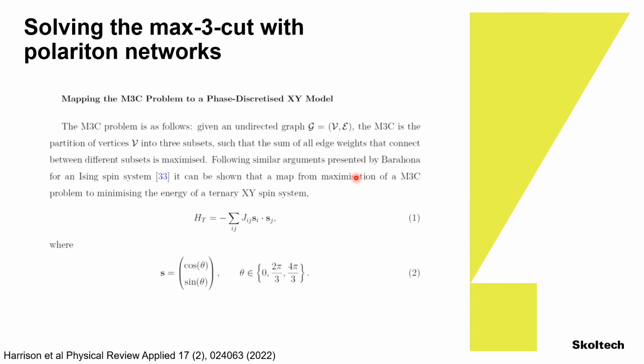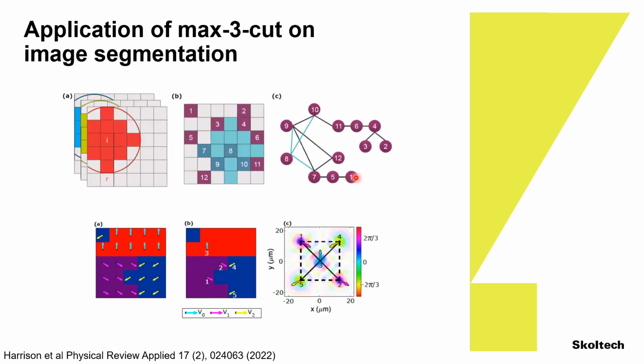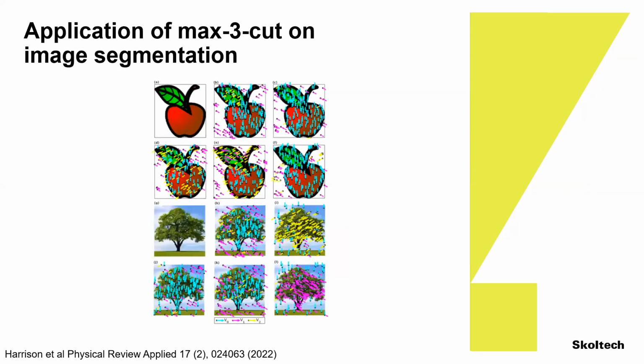And we did this, and we found that actually we can apply it to image segmentation. So for example, we can use a 3-color image, and by putting this into our system, we can actually see that the phases recognize different parts of the object. Yes, so you take a real problem, you map it on the ternary phase space of the polariton lattice, and the system, when it condenses, finds the phases arranged in a way that distinguishes between different objects.